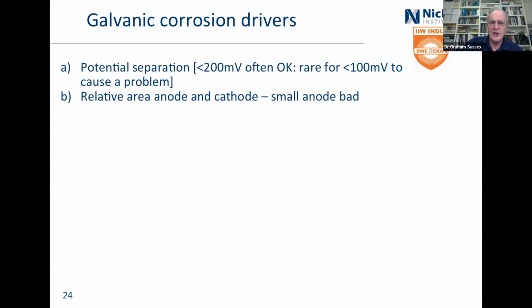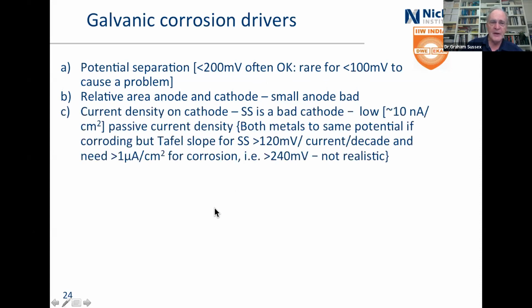Okay, so what drives galvanic corrosion? Potential separation. Less than 200 millivolts is often going to be okay. It's very rare, if you've only got 100 millivolts separate, for it to actually be a problem. It can happen if you've got a very tiny anode and a very big cathode, but it's pretty rare. And that's what this example is about.